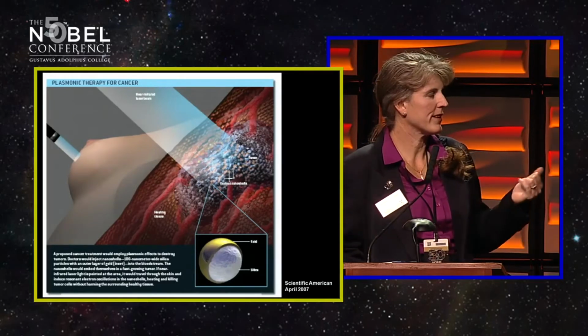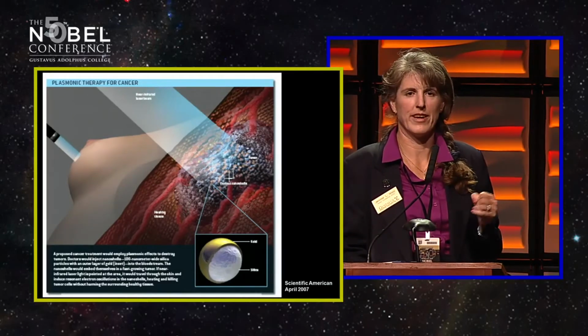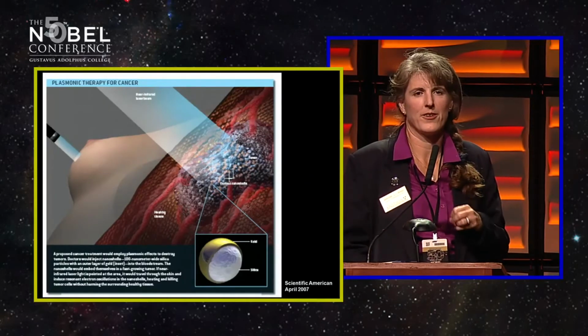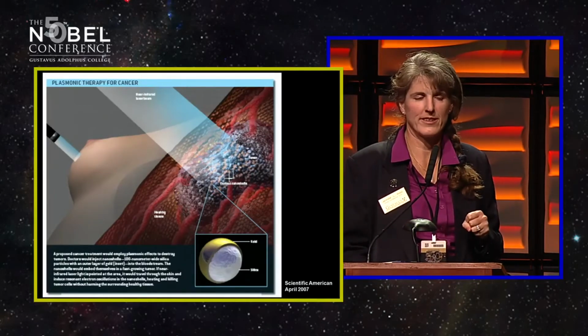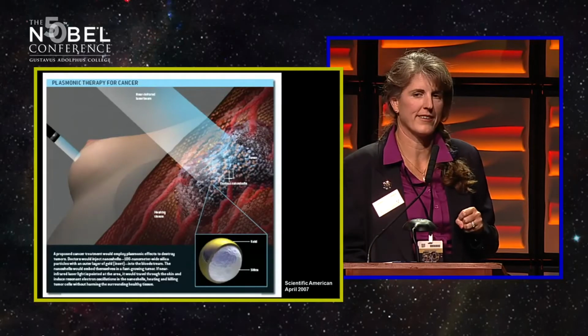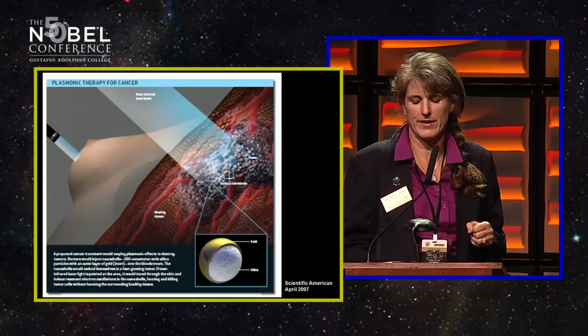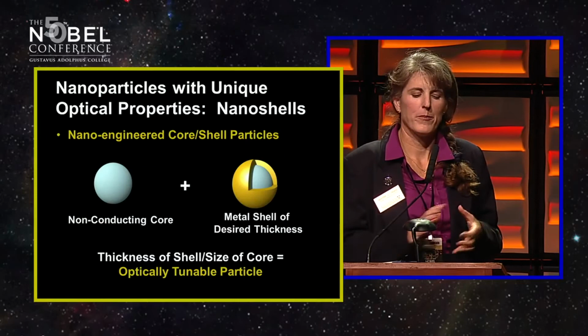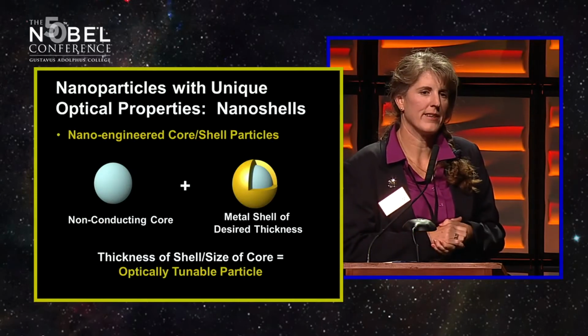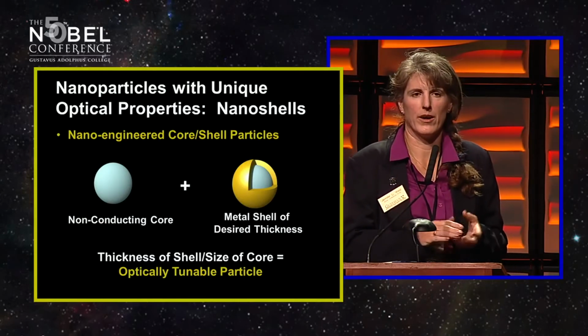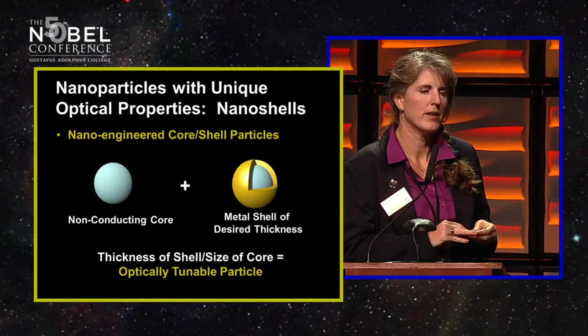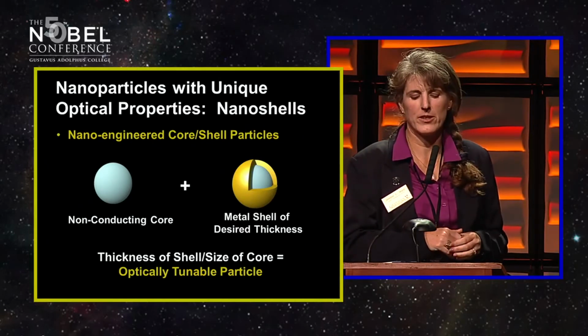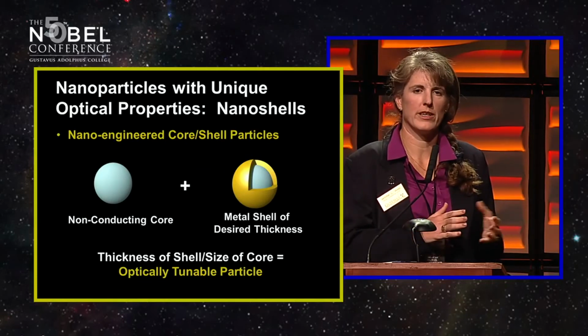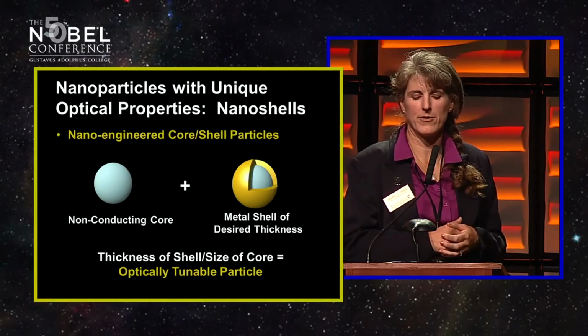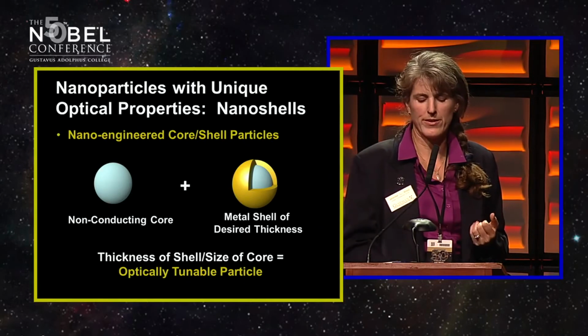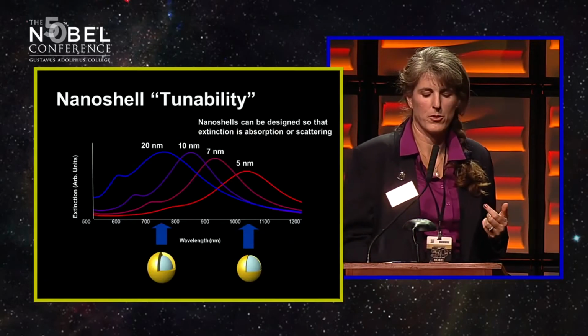So the particles you see here look basically like nanoscale malted milk balls. You have a core material that, for the work I'll show today, is silica, and then a metal coating that's gold. By choosing how we design these materials very carefully, we get very tunable optical properties. So we can change the size and composition of each layer and change where the particles interact effectively with light, and also whether we have mainly absorption or scattering.